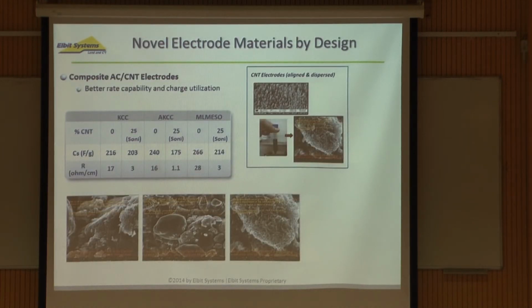Some examples of what we have done by implementing, for example, CNTs and designing composite activated carbon and CNTs electrodes in order to get better rate capability and charge utilization. We started in the beginning when the CNTs emerged. The idea was, oh, you have these great materials in terms of the electronic conductivity, in terms of the strength, and the idea was to implement them as electrode materials.